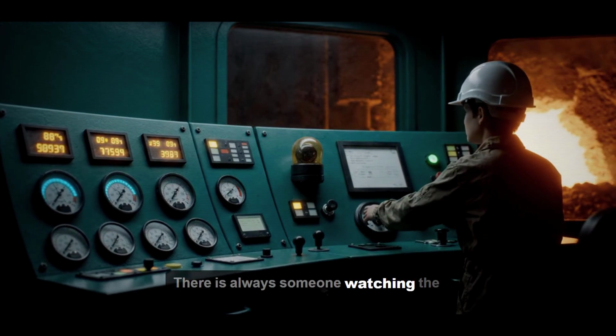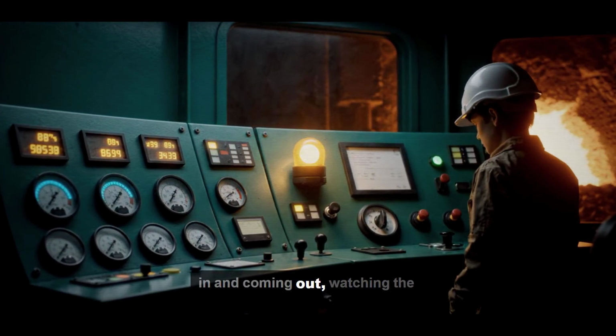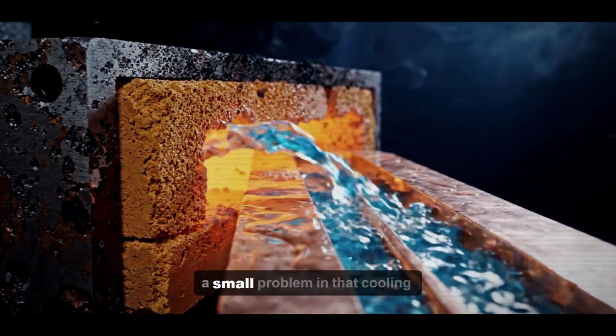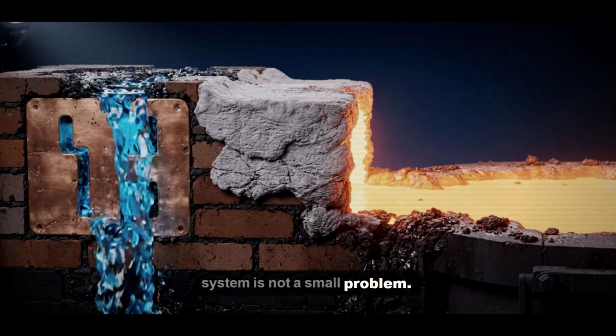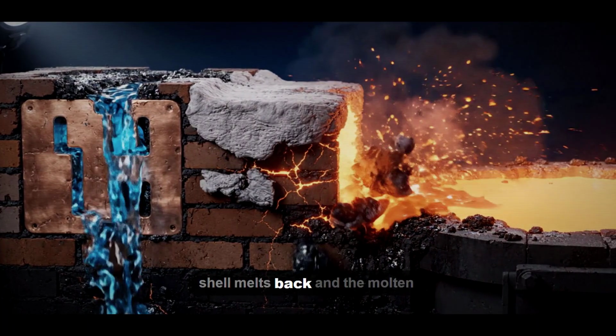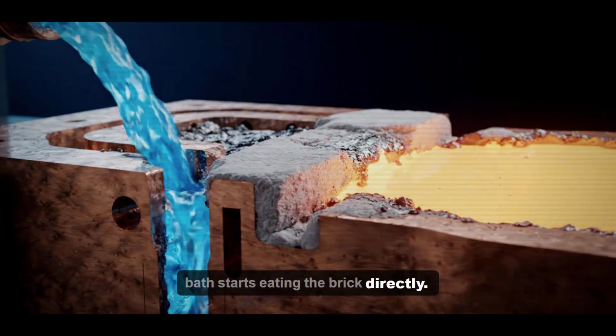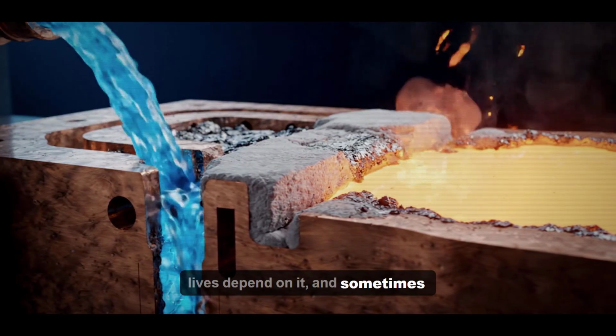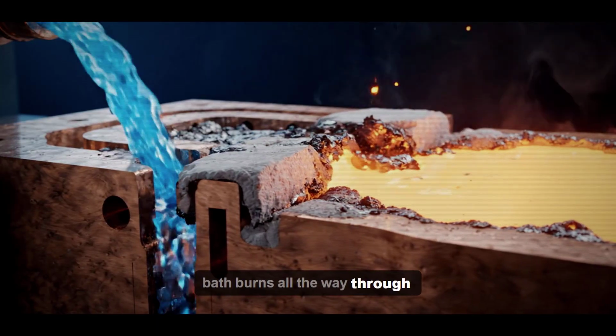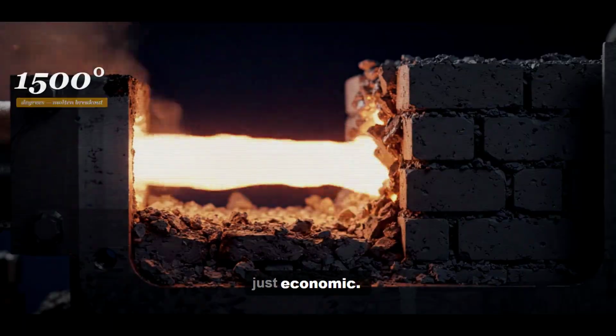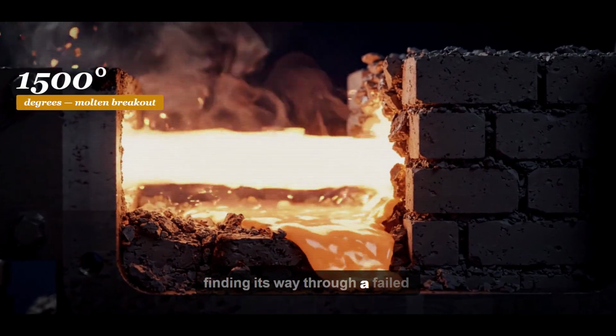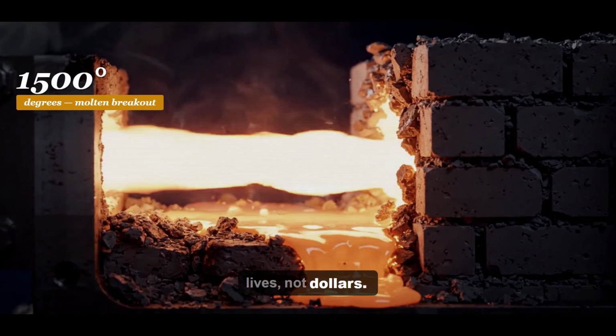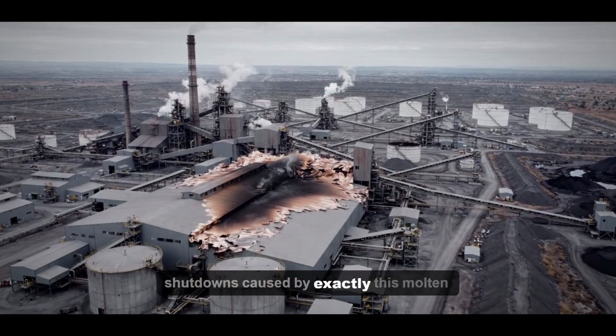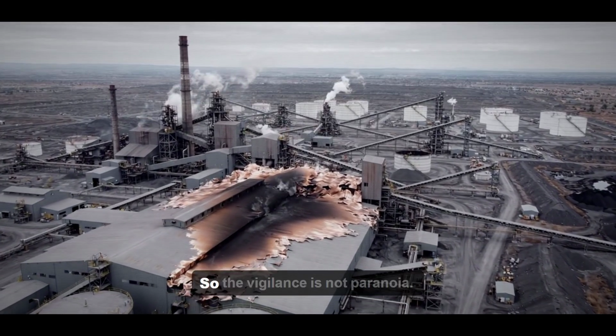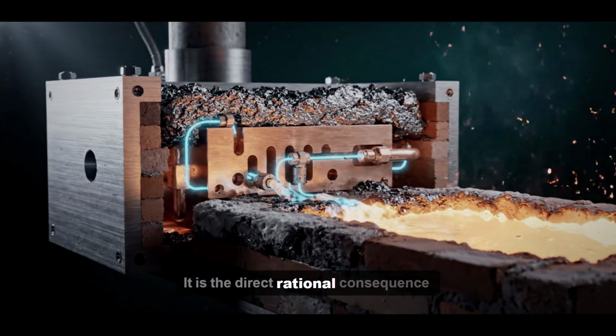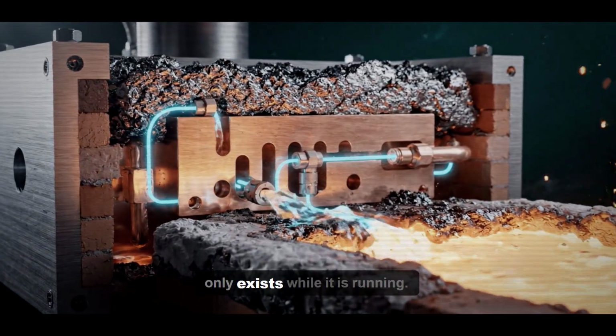There is always someone watching the temperatures, watching the cooling water going in and coming out, watching the heat coming through the shell, because a small problem in that cooling system is not a small problem. If the water stops, the frozen shell melts back and the molten bath starts eating the brick directly. They watch the cooling like their lives depend on it, and sometimes they do, because if the corrosive bath burns all the way through the sidewall, the consequences are not just economic. Molten metal at 1,500 degrees finding its way through a failed wall is a catastrophe measured in lives, not dollars. There have been smelter fires and shutdowns caused by exactly this molten metal escaping where it should have been contained. So the vigilance is not paranoia. It is the direct, rational consequence of running a machine whose protection only exists while it is running.